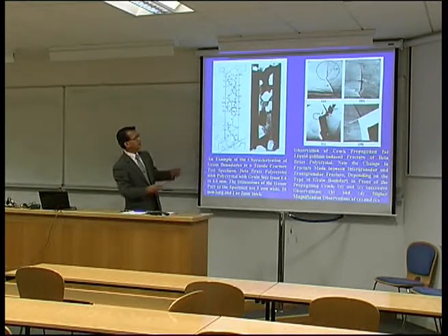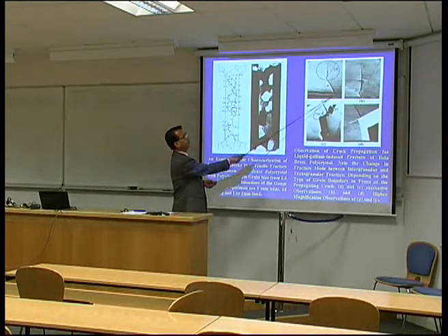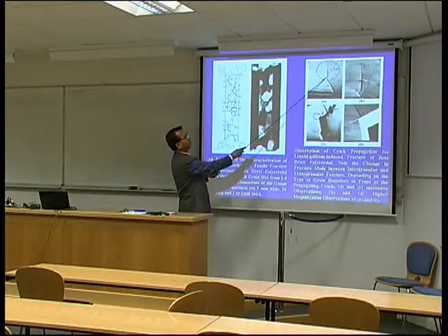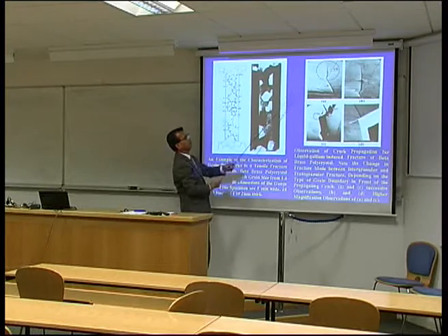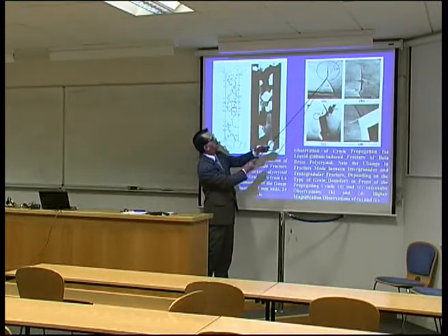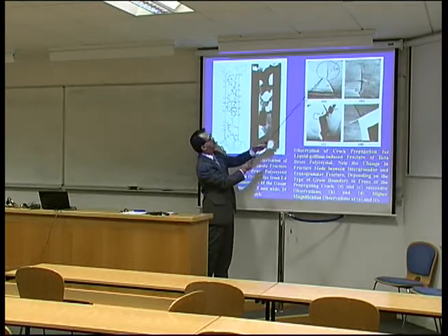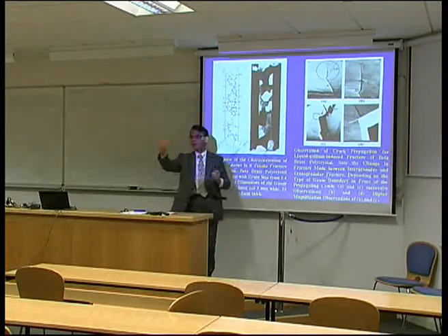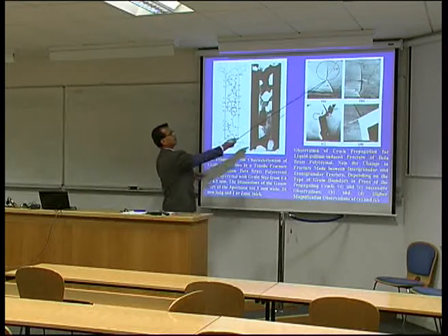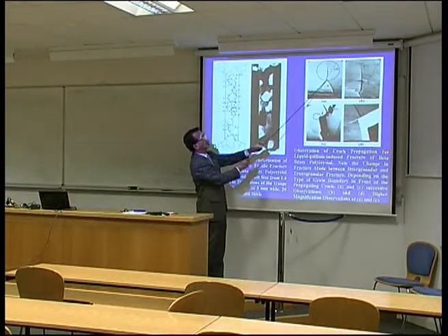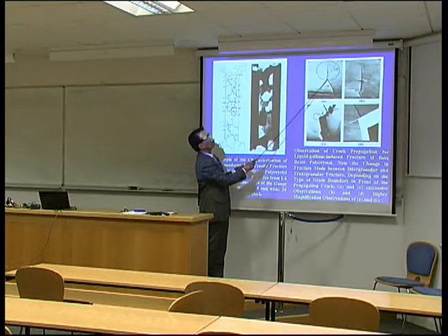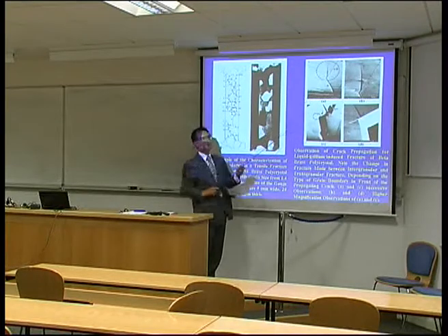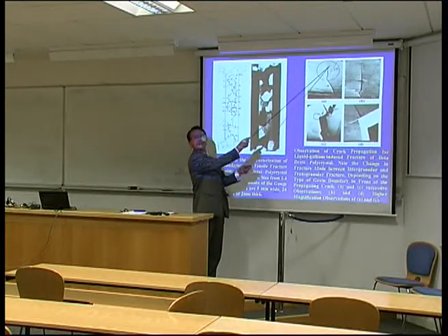But anyway, as you see, the random boundary easily breaks and then the crack propagates. So we can observe the propagation of the crack. And then when the propagating crack meets the triple junction, the stress axis is horizontal, and here is the boundary, and here is the boundary. This boundary has very low normal stress, this one very high, but this is a low angle boundary. Because of its low energy, the crack cannot propagate around this. At a rather higher energy boundary, the sigma 25 boundary, it can break for a while, but again this is still a low energy boundary. So the fracture mode changed from intergranular to transgranular fracture.